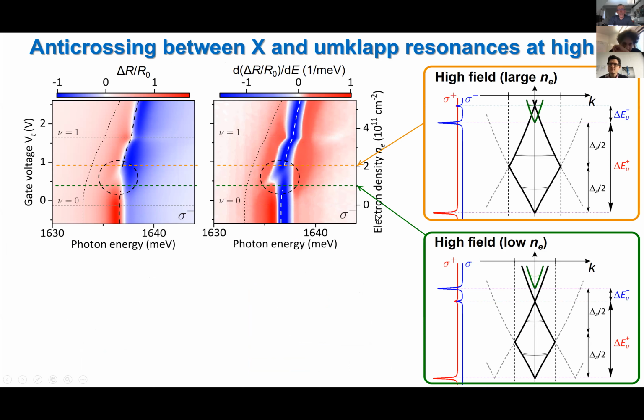And so this is basically nice news. Then we see that on the higher energy side, though, higher density side, that we lose the umklapp peak. So basically, we believe tentatively what is happening is quantum melting. So at these densities, the system is no longer in a Wigner crystal state. And something else happens at nu equals 1.